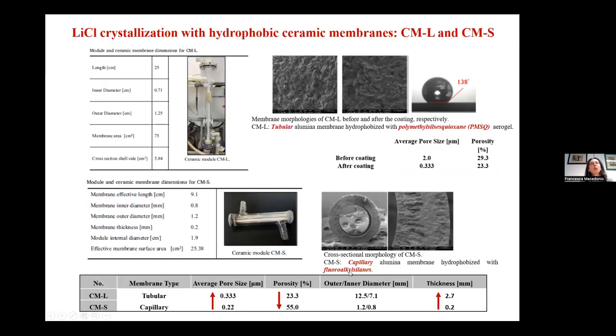Then we tried to see what happened changing the membrane material, to check if other materials can be used for achieving the lithium chloride crystallization. In the previous test, the one that I showed before, membranes in polypropylene were used. Then we also used some inorganic membranes, in particular two different inorganic membranes.